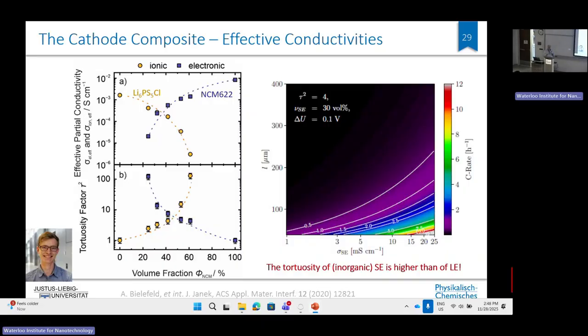Well, like in your lung, where you have, of course, highly tortuous ways for air and for blood in order to have an effective breathing process. So this is the same with ions and electrons in the cell. And here, as a fraction of cathode material, Philip measured the electronic conductivity and the ionic conductivity. And of course, quite trivial, if you have pure electrolyte, the ionic conductivity is high, and pure cathode material, the electronic conductivity is high, because these electrode materials are primarily electronically conducting. Ionic transport is there, but it's not so fast.